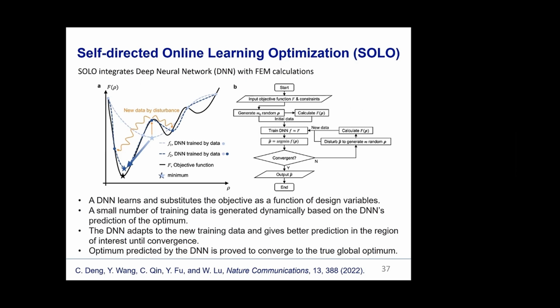We dynamically train a neural network, and this will learn roughly the landscape of the objective function. Then, only in the region of interest, we dynamically generate data and train the machine learning to learn well in this local region. If you look at the figure on the left, we can find that even if the value differs between the neural network prediction and the true value, the position of the optimized point is very close. Because we don't need to learn the entire function, only the function locally at the region of interest, we can dramatically accelerate the optimization.